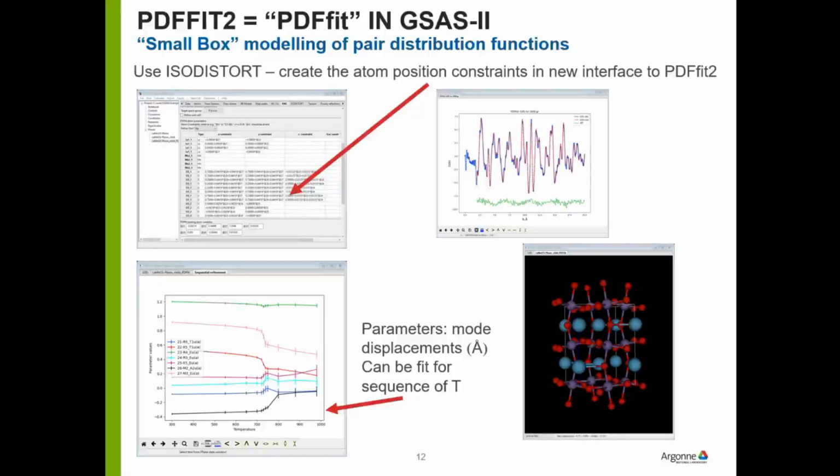And you can notice which ones, some of them don't change hardly at all through the phase transition, and some of them go through rather dramatic changes through the phase transition. And you can then look at and see what happens, whereas in this particular case, it was a rocking of the manganese 6 oxygen onto here. Just tipped in a particular way. You can actually see it. Okay.